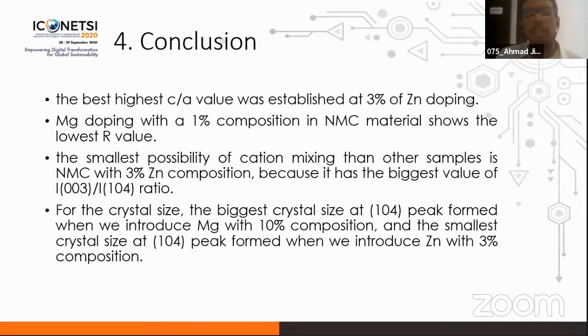And the conclusion is the biggest C per A value was established at 3% of zinc doping. Magnesium doping with 1% composition in NMC material shows the lowest R value, and the smallest possibility of cation mixing than other samples. NMC with 3% of zinc composition. For the crystal size, the biggest crystal size at the 104 peak form is when we introduce magnesium with 10% composition, and the smallest crystal size at the 104 peak form is when we introduce zinc with 3% composition.